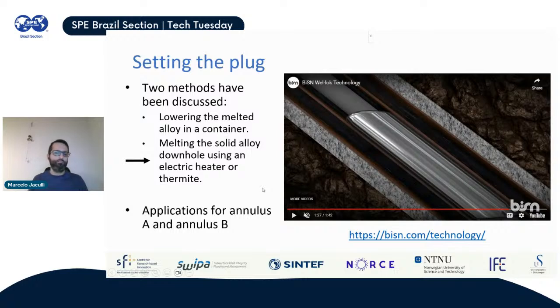And as I mentioned in the beginning, we have applications for setting a plug. It's possible to apply this to settle a plug inside the casing, but you could also use this in place of the cement behind the casing, because it could even help a poor cementing job by pumping extra bismuth, or you could even pump bismuth within the cracks here of cement, which is something that was also investigated by them.